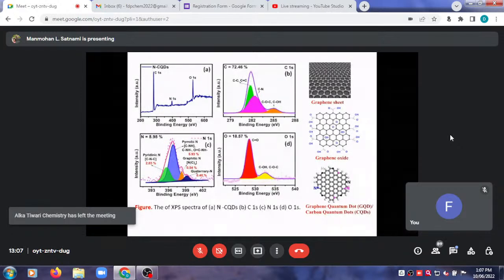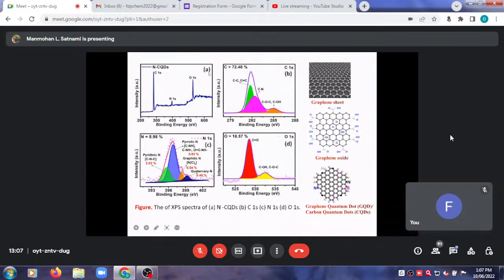After synthesizing that quantum dot, we characterized it with different spectroscopic techniques: through IR, through UV visible spectra, through fluorescence measurement, through TEM images, etc. And then we studied the XPS spectra of nitrogen-doped carbon quantum dot, and it gives a very good amount of information. You see figure number 1A. These are the peaks in XPS. This peak is for carbon 1s, this middle one is for nitrogen 1s, and this is for oxygen 1s.